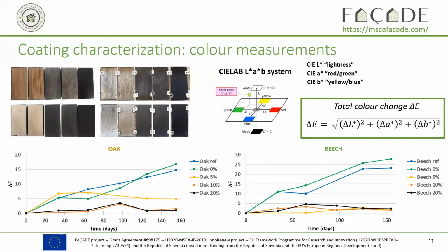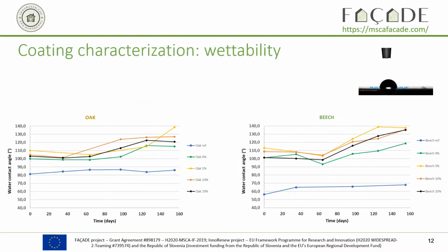And then you can see that for the different samples with 5, 10, and 20% biocarbon, there is a stabilization of the color. And the color change is very, very small, even after 5 months of exposure. Then we looked at the wettability of the surface. We look at this using the water contact angle.